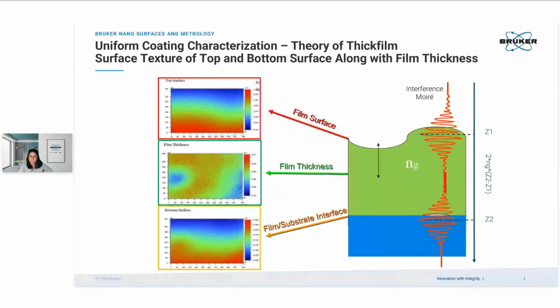So let's now take a quick look at the theory of how we are measuring thick films or the films of materials with WLI. For measuring a transparent or a semi-transparent film, we measure a step from the top of the film to the bare substrate. And then the maximum measurable thickness is only limited by the scan length of the profiler you're using, which is in our case 10 millimeters. So this is the maximum film you can measure.